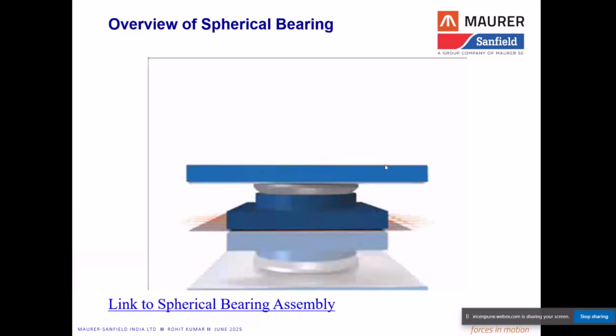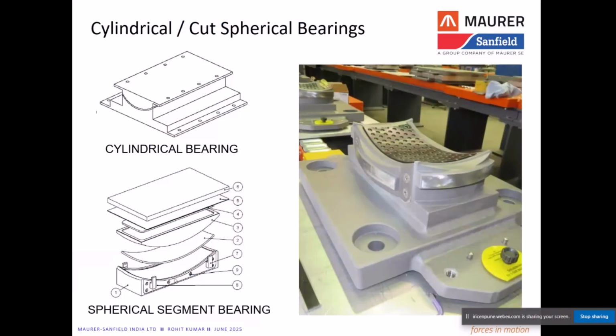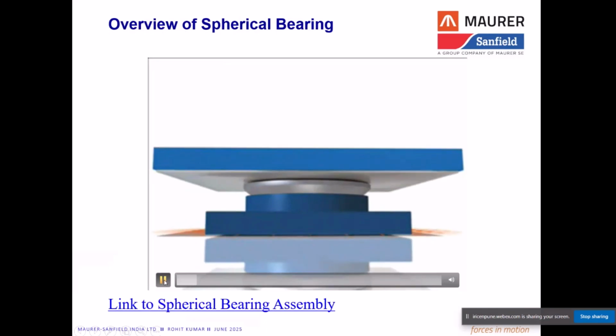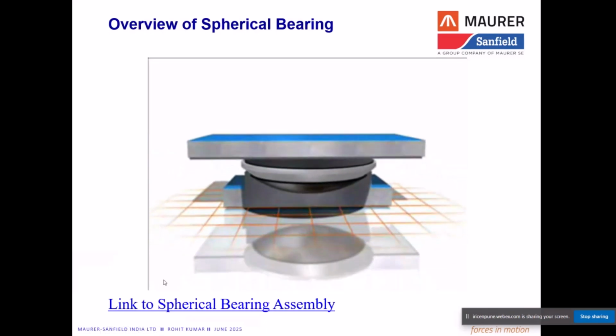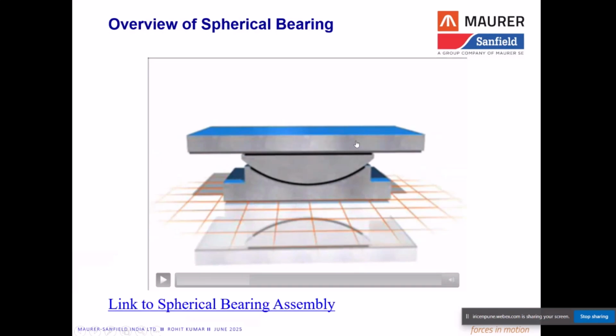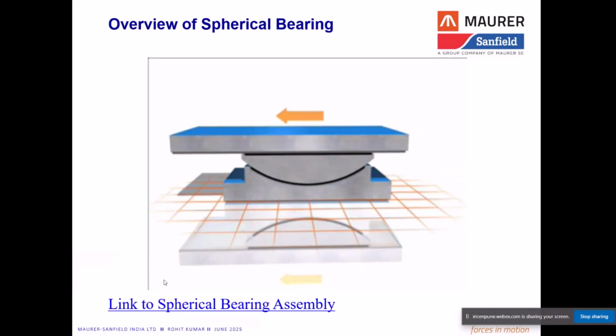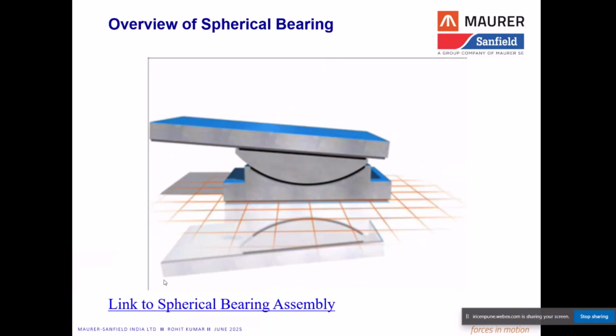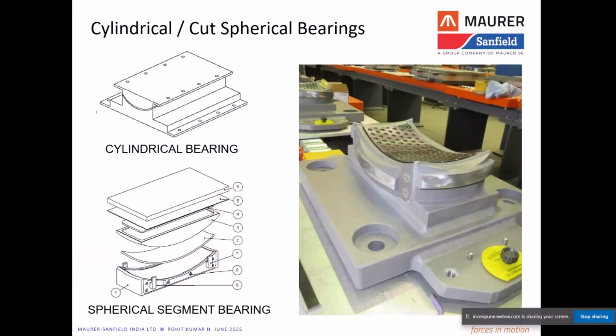Then in 2014, new bearings were introduced after checking all the criteria of the bearings, and their limitations and failures. There was a requirement to introduce new bearings, more or less similar to our rocker roller bearing, but the difference is that there is no direct steel-to-steel contact in the spherical bearing. If you can see, the concept of the rocker roller bearing has been completely used inside this spherical bearing design, but the difference is a thermoplastic sheet used between the steel components to decrease the friction between the materials, and then you can achieve a higher service life of this bearing. So this is the function of this spherical bearing.